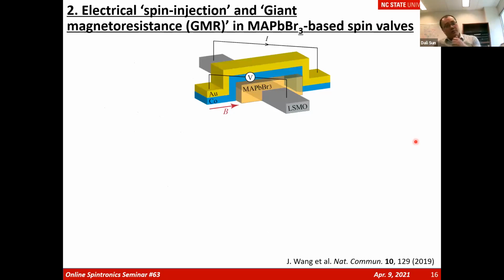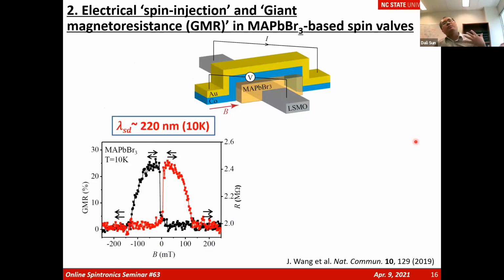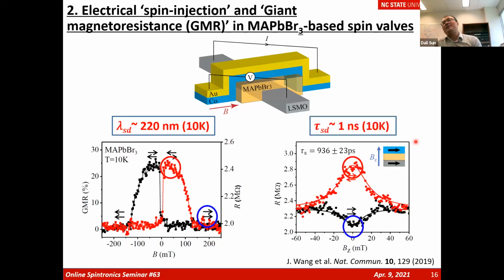So then back to 2019, we used the same materials using a spin valve configuration. We're able to observe very nicely magnetoresistance, using the typical MR responses, the spin diffusion at a low temperature. Even though we have lead as such a strong spin-orbit coupling system, the spin diffusion length can be up to 200 nanometers at 10 K. By applying a vertical magnetic field, we see obviously the Hanle precession indicating the formation or injection of spin-polarized carriers into the MAPbBr3 spacer layer. By measuring the width, we can detect the spin lifetime at 1 nanosecond and 10 Kelvin.